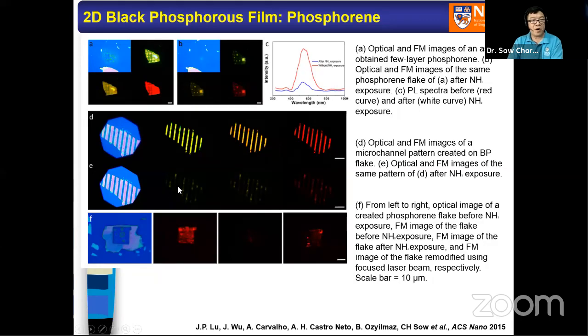The laser-modified thin layer of black phosphorus gives very distinct fluorescence, as you can see in picture D here. And interestingly, when we expose it to ammonia gas, the fluorescence disappears. So you can have a chemical sensor in this particular modified sample, just using a simple focused laser beam, okay?